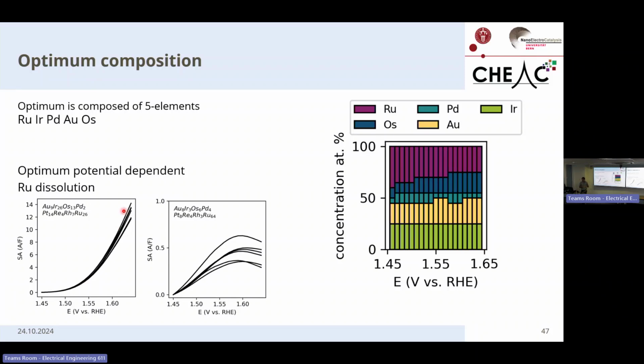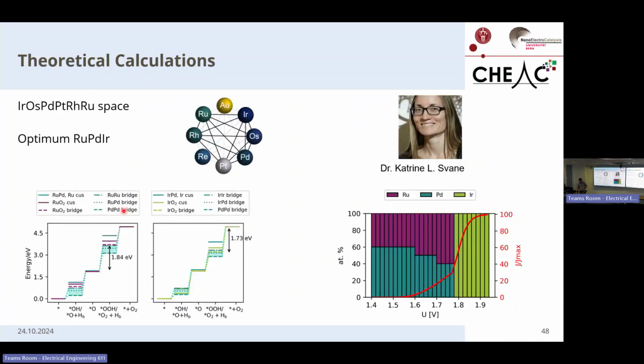But still, we cannot explain why we see 5 elements. So we went back to our theoretician friends, and in this case, Dr. Katrine L. Svane did the calculations, and she modeled the iridium, osmium, palladium, platinum, rhodium, ruthenium space. So rhenium was excluded because we did not observe it ourselves to be incorporated into our alloys, and gold had to be excluded because it was popping out of the surface, giving an erroneous error in the calculations.